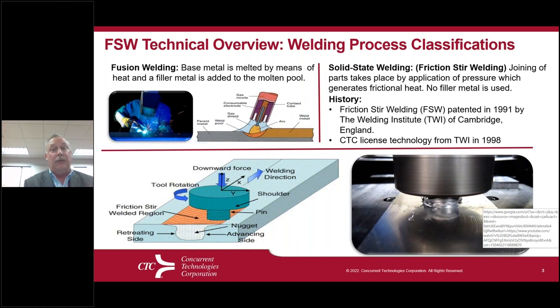The solid state welding, friction stir welding, is quite a deviation from that, in that there is no filler material traditionally. There's no additional heat input from some electrical means applied to the joint. It is done through pure pressure and force applied to a rotating tool in a machine that is plunged into the material, and it generates the frictional heat that basically plasticizes the material. It does not create a melt pool.